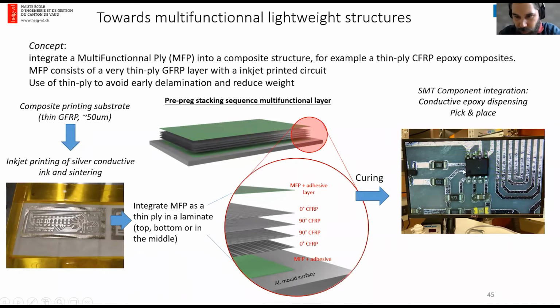And in the end, we can integrate components using surface mount technology, typically here using conductive epoxy and some pick and place techniques. So I have a small example here, which is just, I don't know if you can see my camera, but this is a printed circuit on a very thin GFRP substrate that has been prepared to maximize the adhesion with a pre-preg. And you can see here the circuit. It's a simple LED dimmer where you have a capacitive touch sensor, and we can change the brightness of the LED. So that's a very simple physical demonstrator. But this component can then be integrated in a real structure.